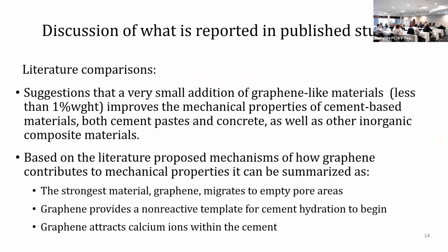Everything that we obtain in a lab, we need to make sense of with what other researchers have done and reported. There is quite a bit of research in concrete where they used graphene type materials, so we looked at that. For our application, because everything is still very fine, it's just cement paste effectively, it seems that graphene really sits in those pores and microfractures. Also, because it does not attract water, there is no water film that forms on its surface. So it's a really good substrate for crystal growth. This is a study that we need to conduct on the pure phases, using only C3S and graphene, to see how graphene actually impacts CSH morphology.